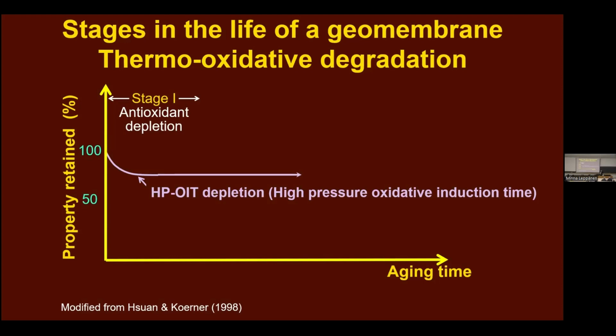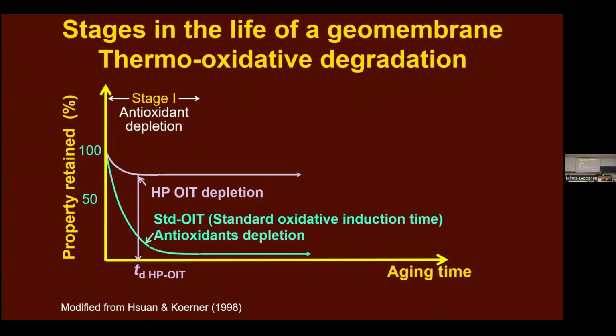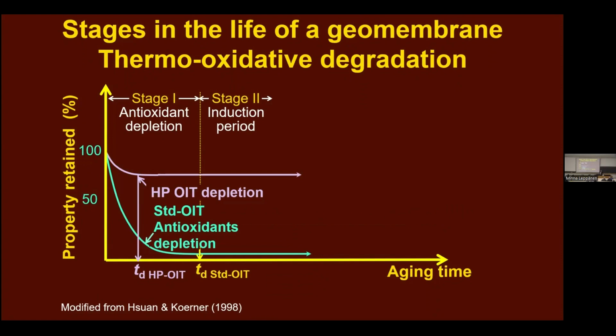So the antioxidants are depleted. HPOIT is depleted here to a relatively high value. So it looks impressive when it starts with a big number, but actually doesn't necessarily mean very much because by the time it's got to a residual value, it's no longer working. So this only takes that time to reach a residual. Here's a standard OIT. It drops a lot further and reaches residual at that time. So the antioxidant depletion is being controlled here, as it often is, by the standard OIT.